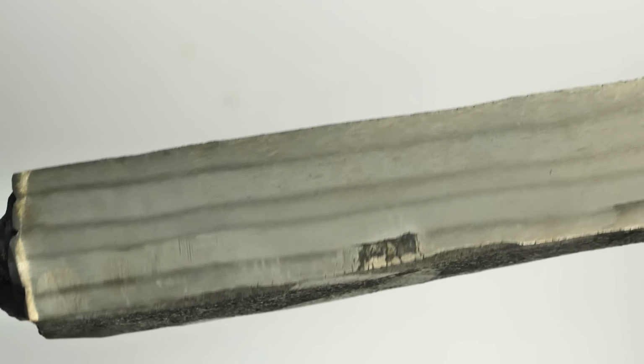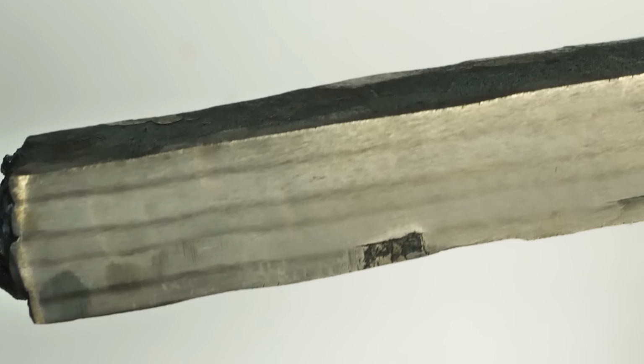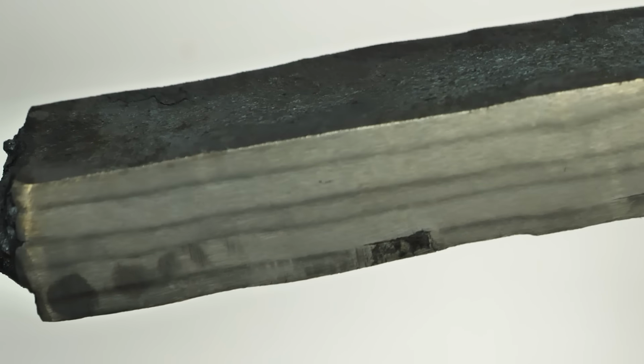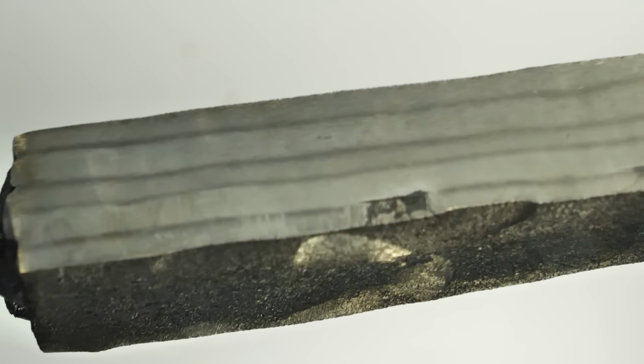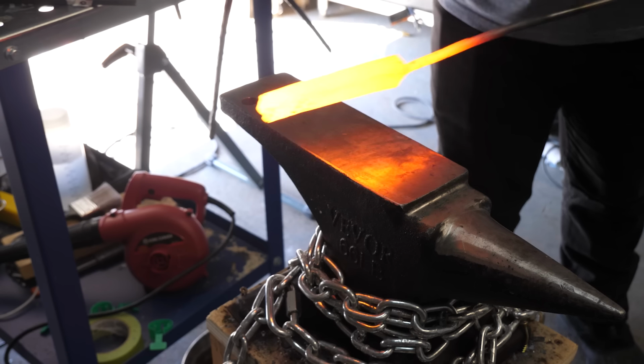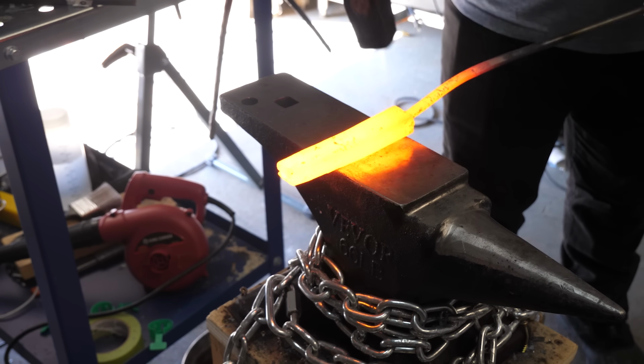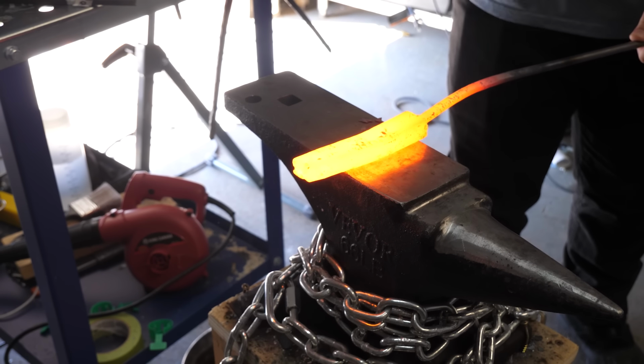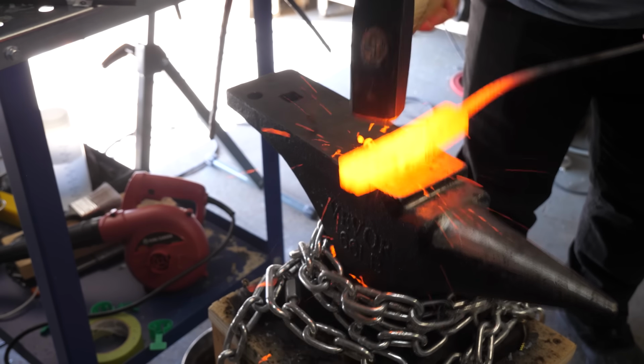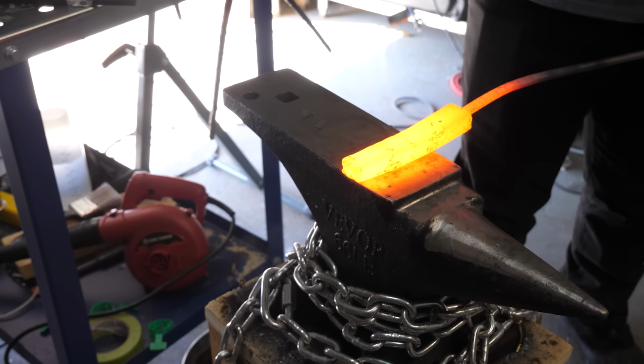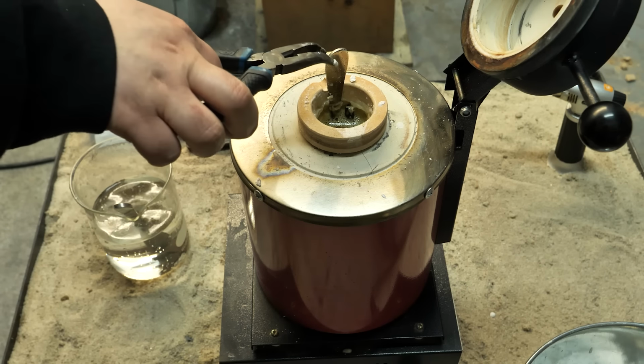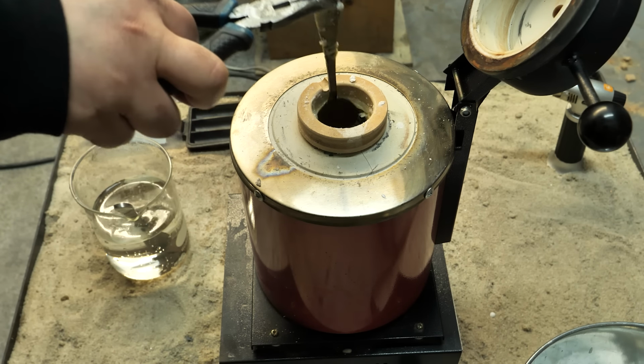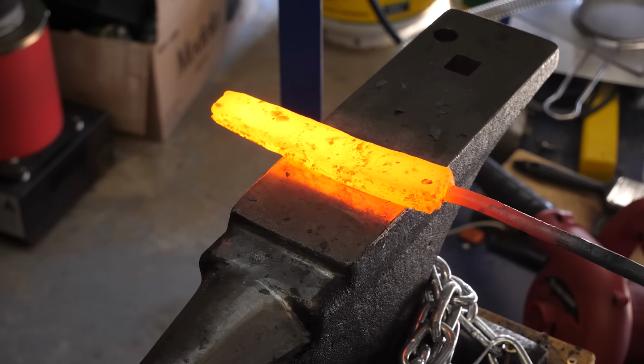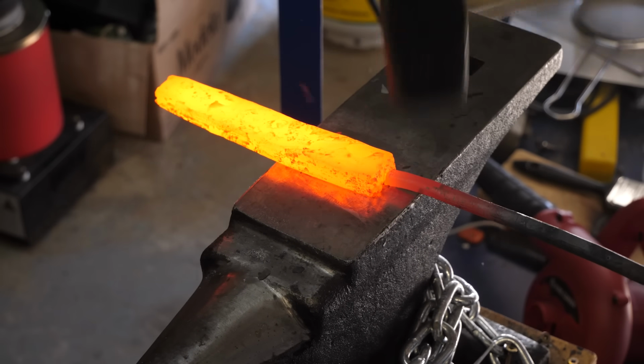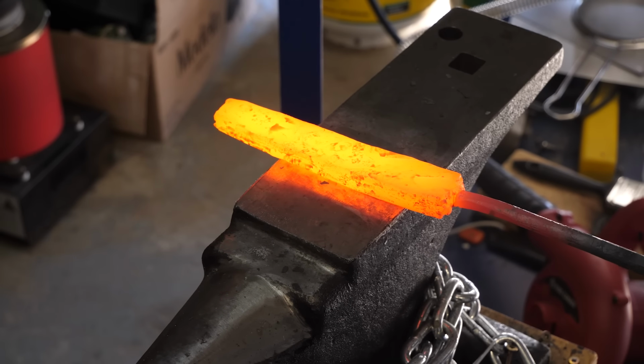The darker parts are where the carbon dissolved in the most, and you can see that even with all that cook time, the carbon didn't penetrate all the way in, which is going to bite us later. While you forge the metal, the carbon will naturally diffuse throughout the billet, so as long as there's enough to keep the total block above a hardenable amount, you're good. But we have some other tricks we'll get to in a moment if we need more hardness. Anyway, this could be chucked back in the fire, and now that we know it's good, I'm going to start working it into the shape of a knife.